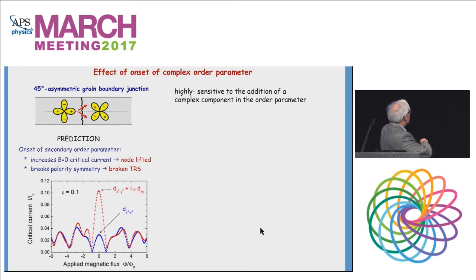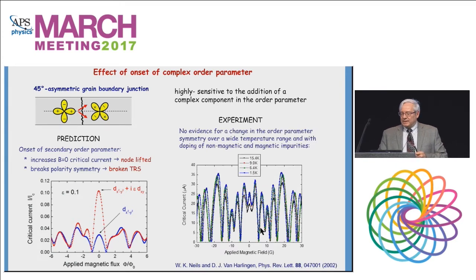It would do two things. It would lift the zero field critical current enormously by lifting the node in this direction, and it would break the symmetry, the polarity symmetry of this device. Experiments done in my group, by William Neils and others, indicated that this was not the case, and you can see that over a wide temperature range, the shape of the critical current diffraction pattern does not change. So this state is simply not there.